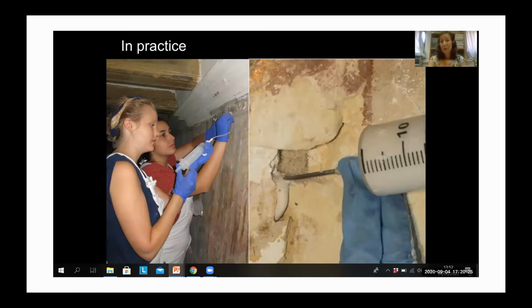So what do we do in practice? We have an injection grout, which is a fluid material, as we will see later. We'll see its composition. And the grout is injected through syringes to which a catheter is applied, or a needle, according to the access point, of course, the delamination type, and also the type of grout. So these grouts are injected behind the plaster, and they are supposed to fill the gap and re-adhere the layers which had this loss of adhesion, and in between which there was a pocket.